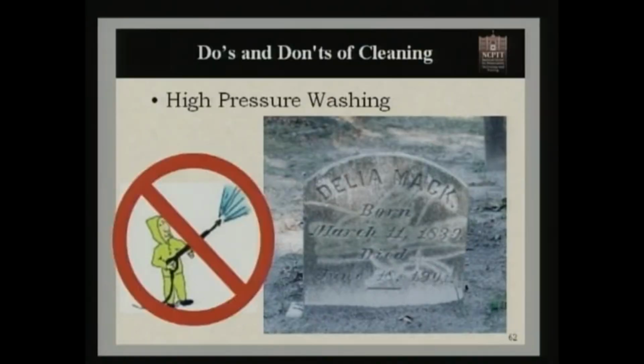Now in this photograph we see here, this stone has not been cleaned recently when this photograph was taken. This stone was cleaned about 2 years prior to this photograph, and what you see is actually those white marks are where the stone has been gouged out. That surface is deeper than the face of the stone, so it's weathering at a different rate.